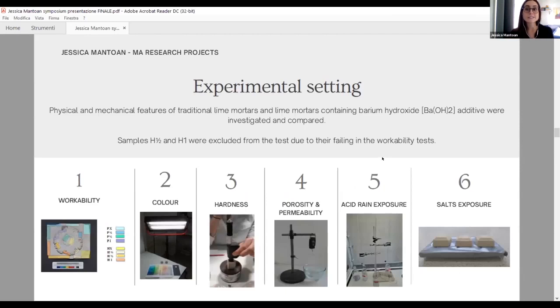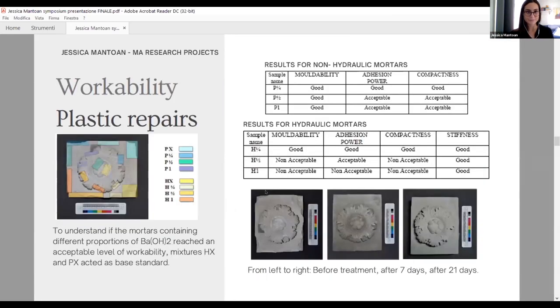After that, I tested all my samples in order to understand if there was any physical change in the mortar. So if there was a change in the workability, hardness, porosity, acid rain exposure, and salt exposure. As already said, from the workability test, hydraulic mortar containing a large quantity of barium hydroxide didn't have a good result. So as we can see, they resulted non-acceptable in workability, regarding moldability, adhesion power, and compactness, making impossible their use in the plastic repair of this three-dimensional limestone.